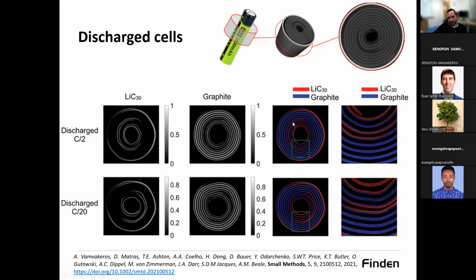And when we looked at it, you can create the composite image here. This has to do with the geometry of the cell and how it's designed and how the various components are placed within the cell. So this has a direct impact on the lithiation process. And this cannot be seen with any other technique. So even if you are a battery engineer, this type of images or results can help you think about how to design a new cell, perhaps, because this type of information is expected, let's say, but it has never been visually shown before. So in this case, the red part here, that is the lithium carbon 30, is where you have the current collector in the other electrode, and at the edges is where you don't have a component from the other electrode.